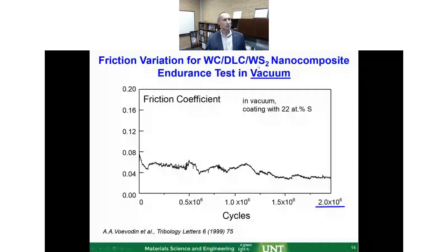This example is a tungsten carbide DLC WS2 chameleon coating, which has carbides as a hard matrix, DLC for lubrication in the humid environment, and WS2 for the vacuum. What is shown here is a vacuum test. We have over 2 million sliding cycles, so it's a very long test. As you can see here, the friction is actually dropping down, and there is no way to show that it's going to fail. In fact, it will run forever, because once it develops the tribofilm and supporting it, the wear pretty much drops down to non-existent. Okay, what's happening in terms of mechanism? Well, there is tribofilm formation.